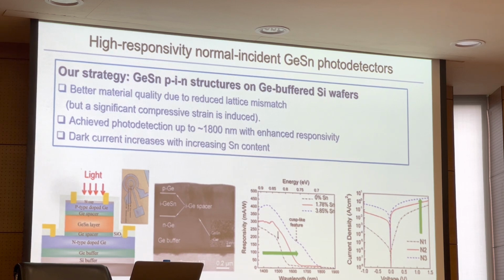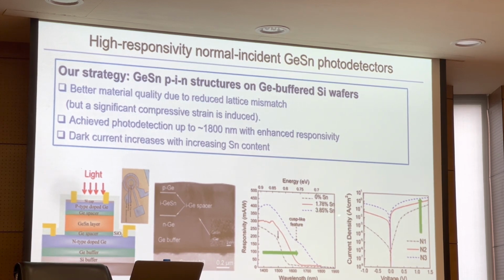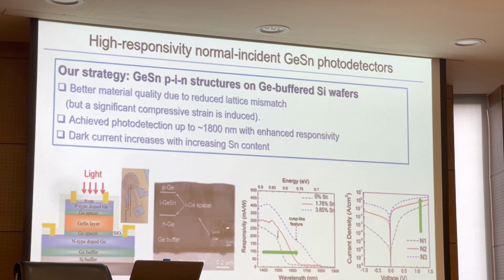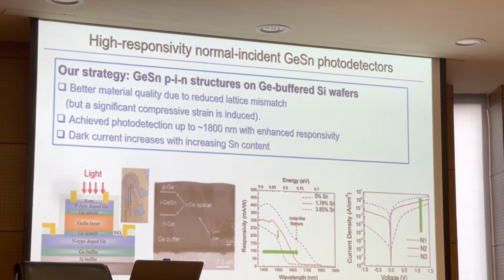Here we grow three samples with different tin content: 0%, 1.78%, and 3.85%. This figure shows the responsivity spectrum for the devices. For the pure germanium sample, as you can see, the cutoff wavelength is around 1.5 micrometer.